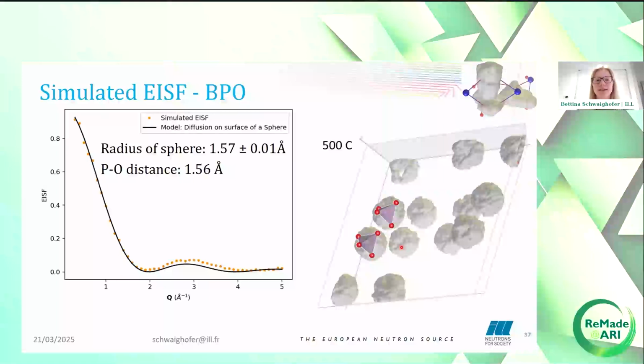For BPO, the agreement between the model of diffusion on the surface of a sphere and the experimental data is even better, and the radius of the sphere and the bond distance agree very well. Since the phosphorus atoms have a stronger preference to be tetrahedral, the spherical description fits this better than for the BVO even. So now from this and the good agreement with the IRIS data, we can say with quite strong confidence that what we observe on IRIS are the rotational motions in the dopant sublattice.